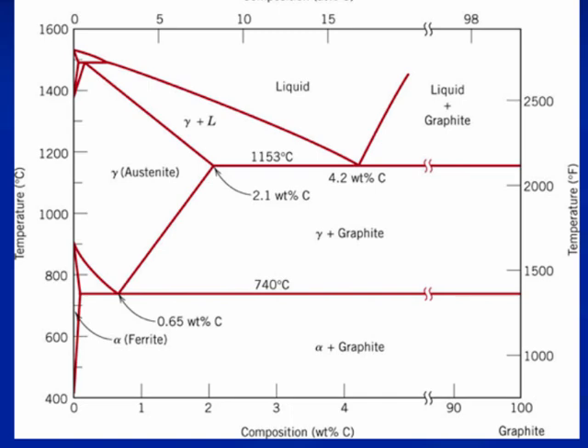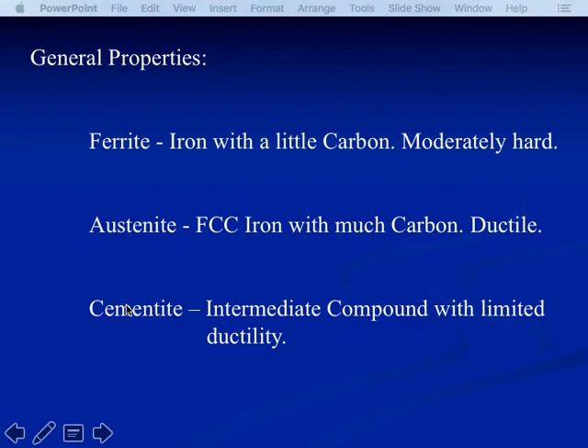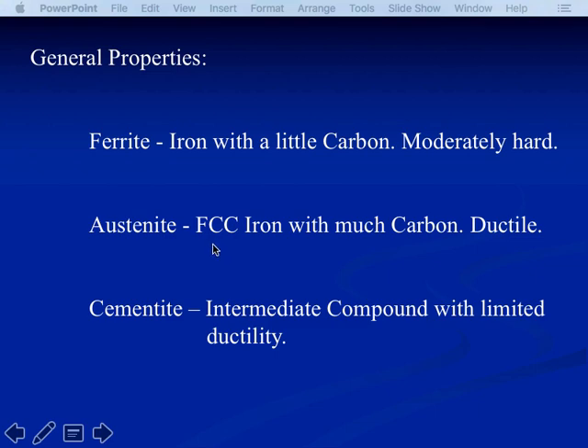What we need to do today is get some basic terminology squared away. There's the eutectic and the eutectoid. Notice that the austenite single-phase region runs out to about 2% carbon. The high-temperature form is FCC iron, and here's your BCC iron — ferrite. The low-temperature form has very, very poor solubility, only about 0.02%. Ferrite is alpha iron, iron with very little carbon, moderately hard, but BCC with limited ductility. Austenite is FCC iron, has a lot of carbon, and is quite ductile, which is why we form iron at high temperature in the austenite state. Cementite is an intermediate compound with limited ductility — Fe3C is the chemical name.